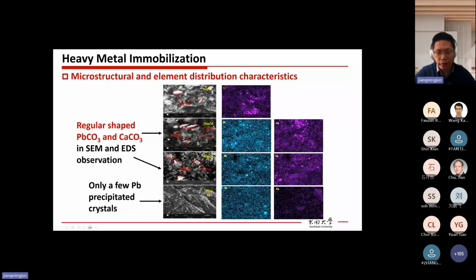And from the SEM graphs, we could see the bright spots in this graph and this graph. Both of them represent the crystallization phases. However, for the 100 millimole case, firstly, we couldn't spot these crystals, both calcium carbonate and lead carbonate. Then from the EDS scanning results, we can see that we don't have so many bright spots compared with previous cases. It means that we don't have a lot of crystals in these cases, and this can demonstrate the retardation effect of high lead concentration on MICP.